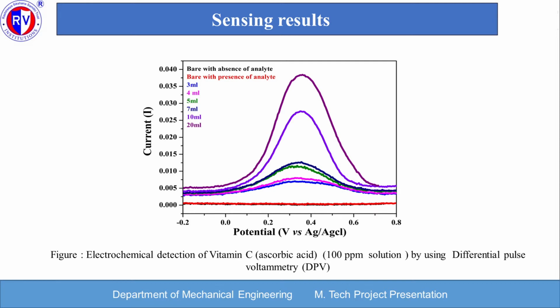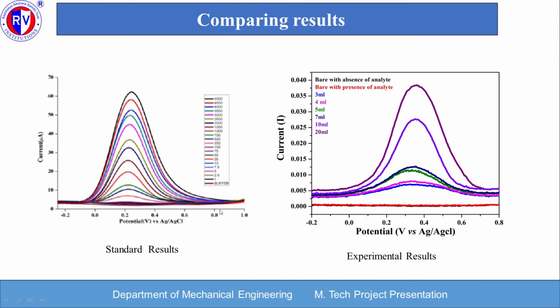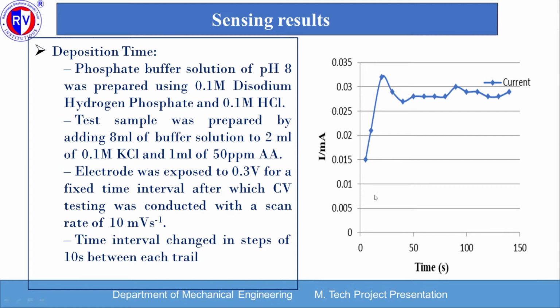This is the differential pulse voltammetry of sensing vitamin C, ascorbic acid. As you can see here, as the concentration increases, the detection level also increases and the graph also increases. These are with the bare electrodes, and these are the concentrations of 3 ml, 4 ml, 5 ml, 7 ml, 10 ml and 20 ml. This is the comparison of the results with the standard results. This is the standard result and this is our experimental result, which is in agreement with the standard result.